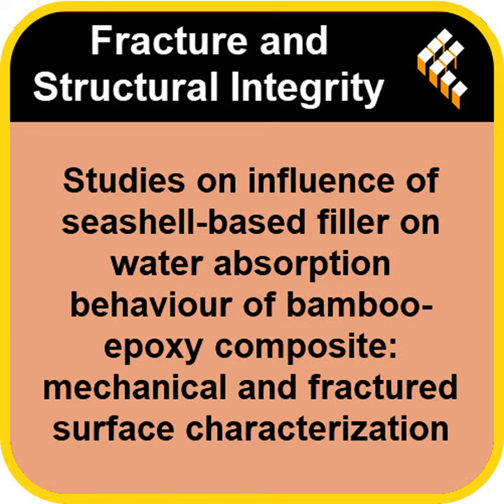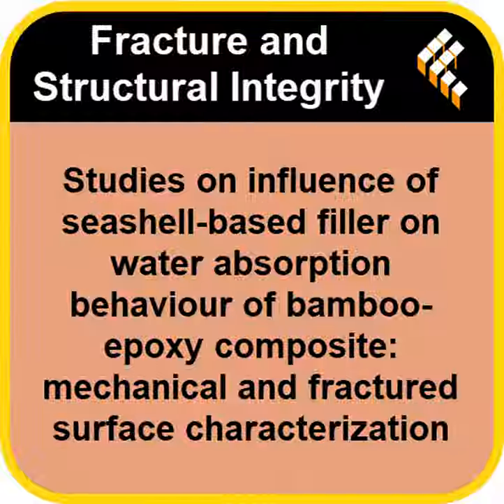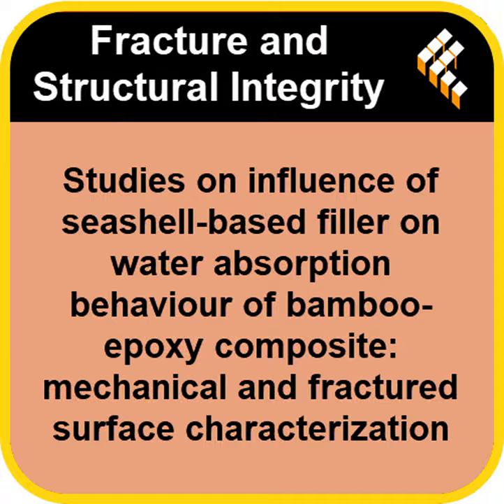Okay, that's the water uptake. But the real question is, does less water mean more strength when wet? Connect the dots for us. That's the crucial link. Let's look at the control sample again, the one that soaked up 5.85% water. When tested wet, its strength just collapsed. How bad was it? Compared to its dry strength, it saw a 52% reduction in tensile strength and a 43% reduction in flexural strength. Basically cut in half or worse.